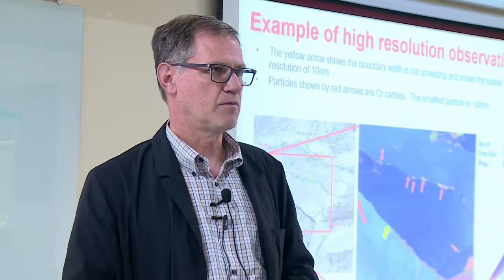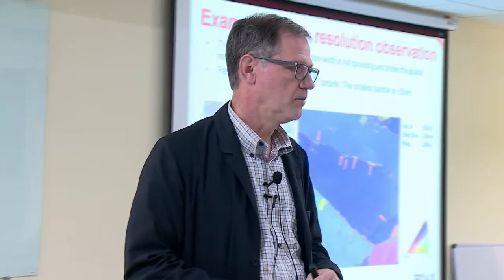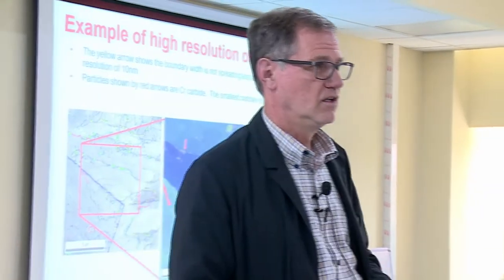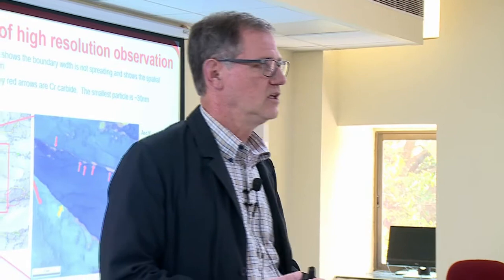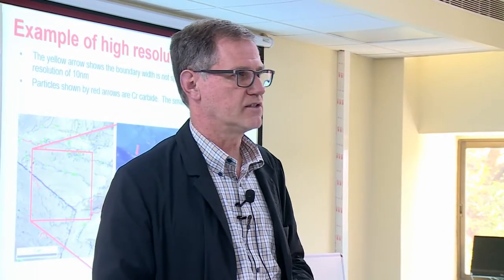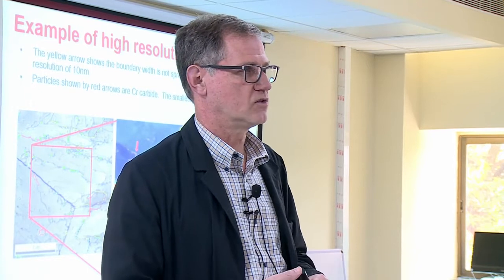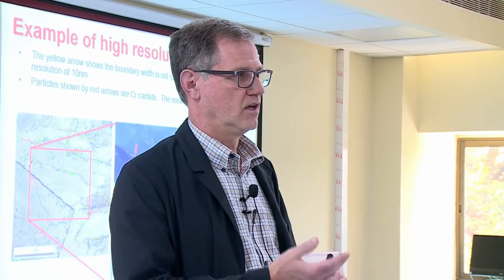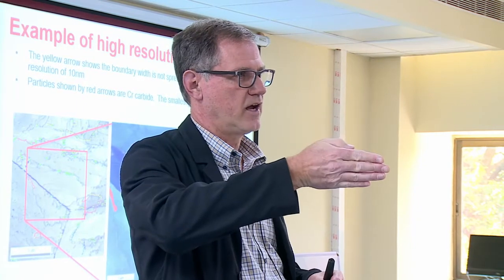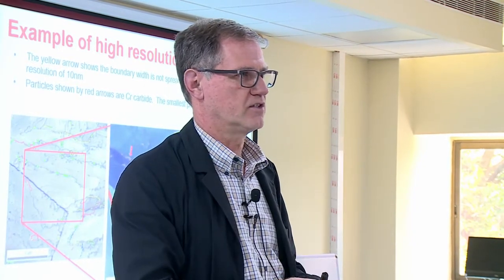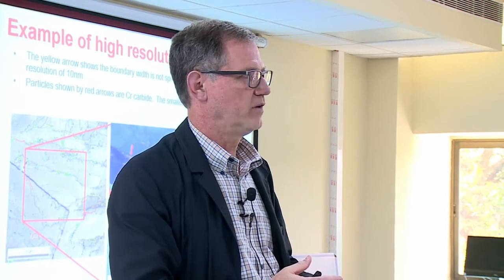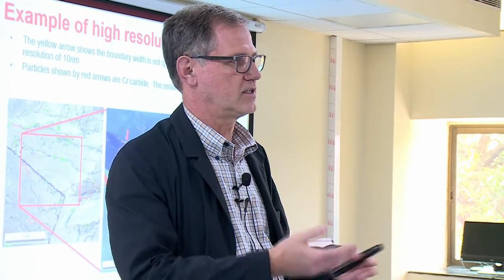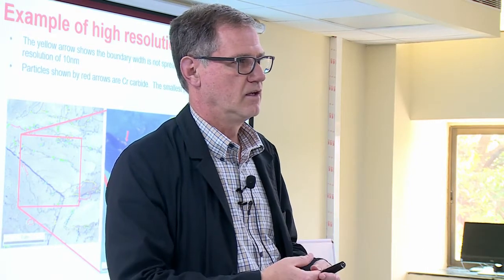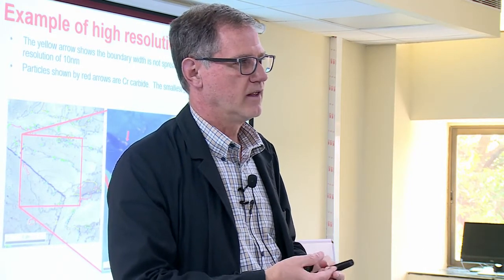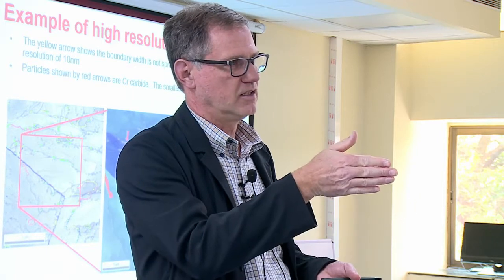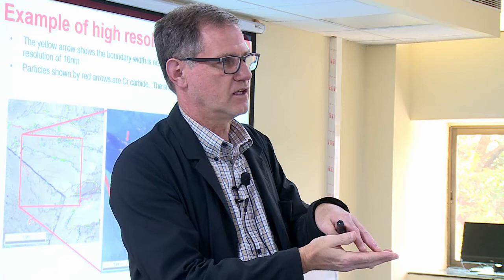We can do EDS simultaneously with EBSD, and we can do forward scatter or back scatter simultaneously. But it's difficult to do a lot of the other techniques, for example, WDS or CL, because with the high tilt, a lot of the geometries become very difficult for some of these other techniques. And so what I've done, for example, where we wanted to use WDS to look at the X-ray signal, is we did that flat, and then did our EBSD tilted, and then correlated the two data sets together.